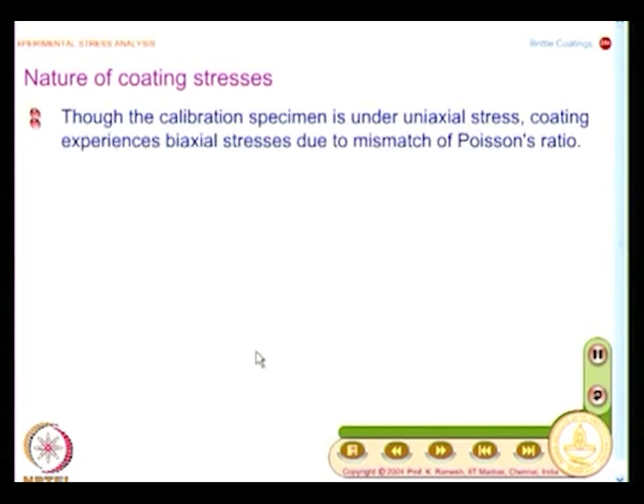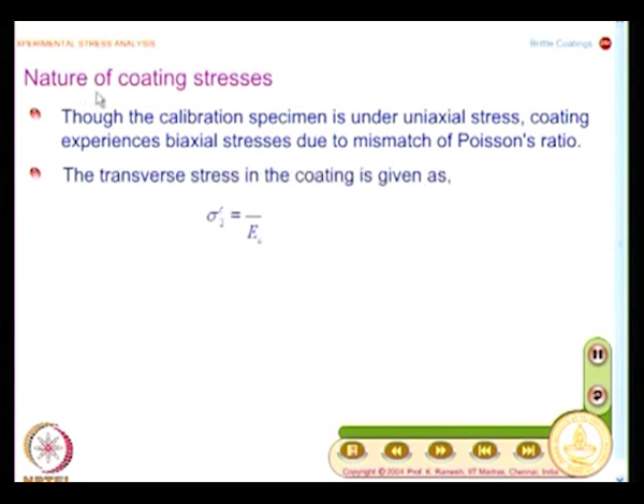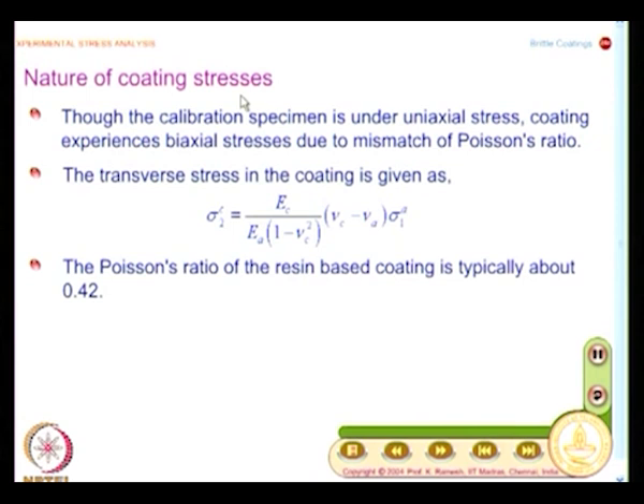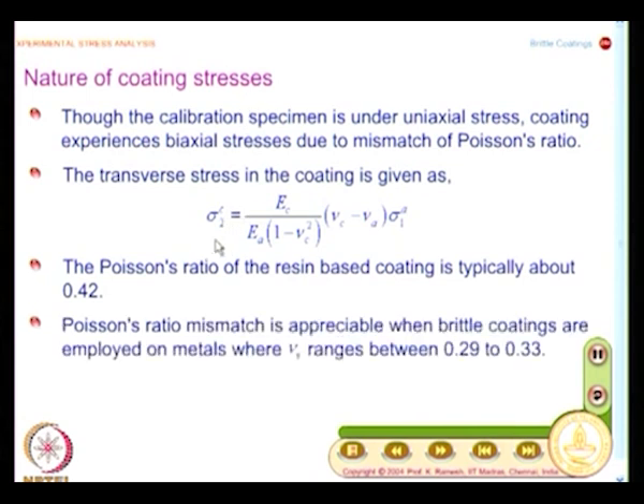And I had already mentioned to you that even for a uniaxial specimen stress, the coating in general will have biaxial stress. That is what I am going to look at. And from the expression that we have seen for the coating stresses, you readily get, because the specimen now used is aluminum, sigma 2 c equal to E c by E a into 1 minus nu c squared, and you have nu c minus nu a into sigma 1 a.